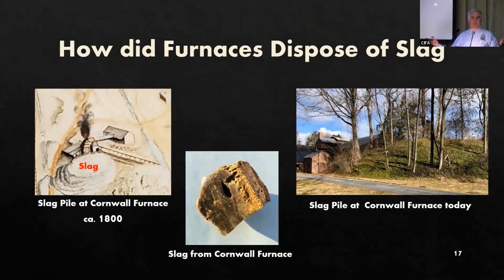So how did the furnaces dispose of all this slag? Well, in the early years of furnace operation, most of the slag generated by the furnace was disposed of relatively close to the furnace. You can see on this slide, on the left-hand side, an illustration of the Cornwall furnace from about 1800. And you see that white pile there, which I've labeled in red letters slag. I added the slag, but the rest of that illustration is untouched from how it was produced in 1800. After the slag was tapped from the furnace, it was allowed to cool on the sand in the casting room floor, and then it was broken up, loaded onto wheelbarrows, and taken outside and dumped in that slag pile.